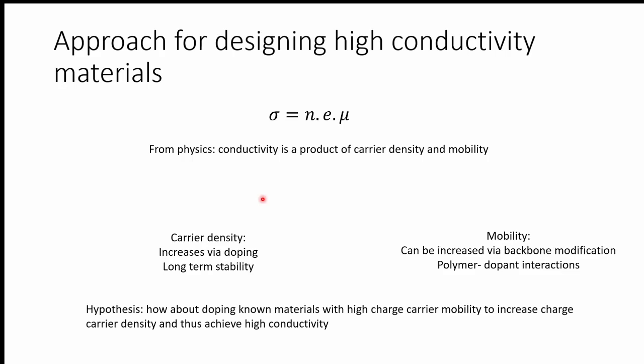Now, as for the mobility, since we know that has already been done, we have a lot of structures to pick out of, right? And the way for us to modify it, if we don't like any of the structures in the literature, we can design new polymer by modifying their backbone and by modifying the polymer-dopant interactions. Because you can imagine when you have a doped polymer that is negatively charged and you have the counter ion which is positively charged, if the Coulombic forces are too tightly bound, if these two charges are tightly bound, you cannot have your negative charge on the polymer just go wherever it needs to transport charges. It will stay bound. So this is one of the things that we try to address, or people in the literature have tried to address.